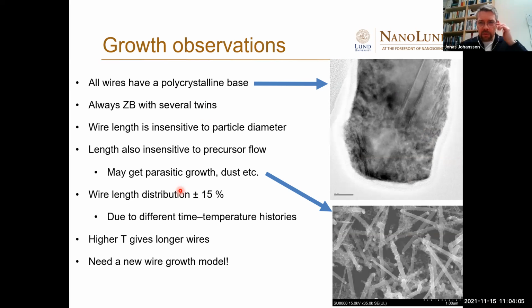And from our observations, we see that all wires have a polycrystalline base. And this, we think, is because it nucleates from 1 liquid gold particle. So it has to nucleate several attempts, and then it finds 1 good growth direction. So it starts growing, but there seems to be some attempts before taking off in one direction. The wires are always zinc blende, but with a lot of twins.